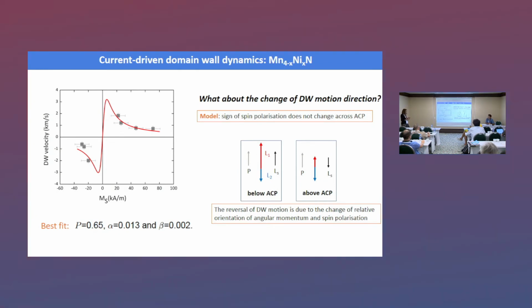Okay, then it's fine. So the last discussion was about the change of domain wall direction. In the model that I just discussed, the change of the domain wall direction is due to the fact that across the compensation there is a change of the relative direction between the angular momentum and the spin polarization. This was the case if you take platinum, gadolinium, cobalt: the spin polarization belongs to the cobalt, the ferromagnet that would be responsible for the spin polarization, and then the direction of the motion will change across the compensation where the magnetization changes sign.